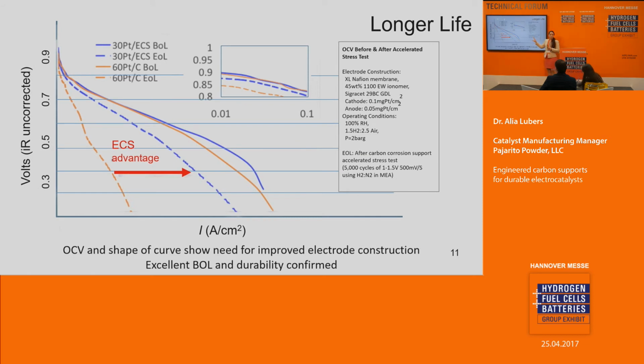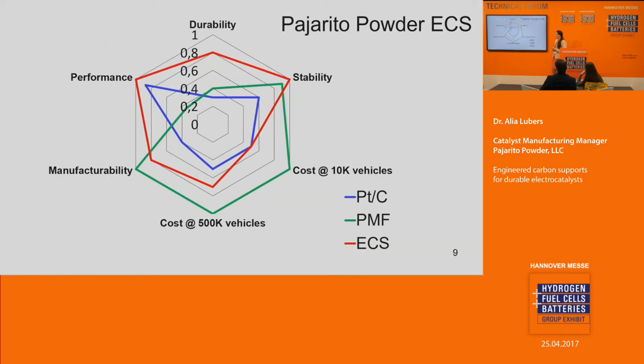Although we can make large improvements in actual testing, these polarization curves show that with our platinization method and MEA fabrication, we are able to match or produce more current using our carbon and our platinization method than in a conventional catalyst. When we apply the accelerated stress test, we can see that our carbon is able to reduce the amount of carbon corrosion compared to a conventional platinum on carbon catalyst. So this is a real testament to the stability and durability of the carbons that we make. So just to look at this again, the material characteristics I showed you contribute to the performance and also the durability and stability of our carbon supports compared to a conventional platinum on carbon catalyst.